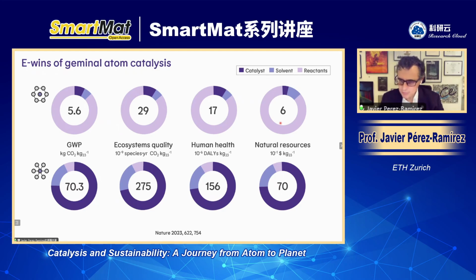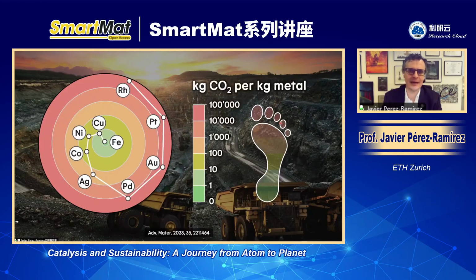In this example, because it's copper based catalysis, most of the burden, as I have shown, is on the ligand of the homogeneous system. If you now go into noble metal catalysis, noble metal catalyzed processes, the biggest burden will be always on the metal. And that's because noble metals have a huge footprint. To produce 1 kilo of platinum, we emit 81,000 kilos of CO2. And that's why having easy to recover catalysts like solid heterogeneous catalyst, and more particularly atomically dispersed heterogeneous catalyst, delivers huge benefits compared to homogeneously catalyzed processes, which are used today for producing fine chemicals and pharmaceuticals.